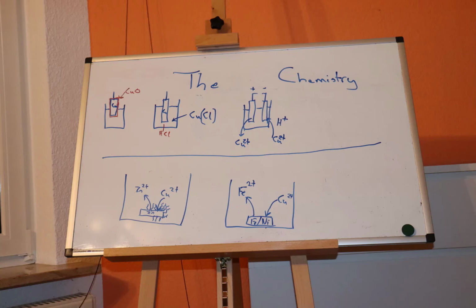On the deposition side, some interesting things are happening too. So if we throw in our zinc-plated washer, I think it was a washer, then zinc dissolves and copper deposits on it, but the copper crystal structure doesn't fit on the zinc at all. And so instead of growing a flat, nice layer on the top of it, it grows little tiny spikes and towers, whiskers on the top, which are easy to remove and appear to be black.